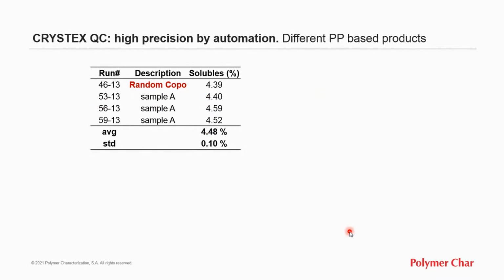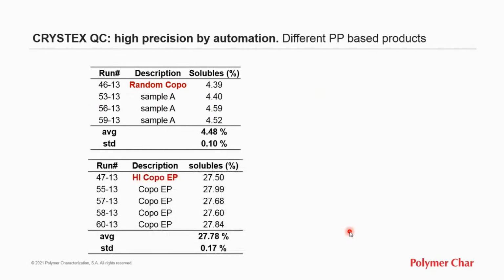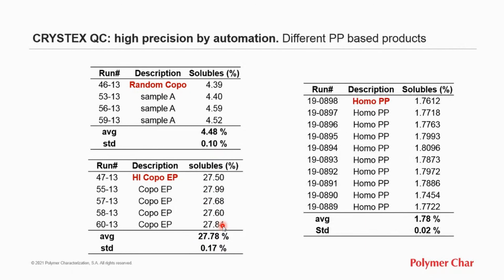High precision is obtained due to the full automation of the method. Here we see the measured solubles for two samples of very different levels, around 4.5% and only 0.1% variation. And a second copolymer with larger solubles of around 28%, still with very low error or variation. Also, homopolymers tend to have a very small solubles fraction. The precision is quite good. In this case, we have a homopolymer with less than 2%, and the precision is very good.